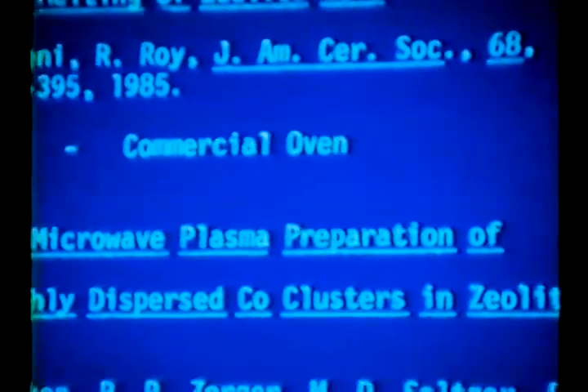Well, here's an example. A picture's worth 1,000 words. Here's this plasma here. Here's the metal carbonyl. So we pull a vacuum through here to get all the gas out. Adsorb the metal carbonyl onto the zeolite. You can see it's a white powder inside of here. Then we have this microwave cavity, and we turn this on. When we're doing the reaction, there's usually a cage around here, because you know microwaves are sometimes hazardous to our health. We have to put a metal screen mesh around this. We put a dewar around this, and we also blow liquid nitrogen onto this material to keep it cool. And then we have these fittings and stopcocks, greaseless lines, so we can bring this into a dry box and load it into a catalytic reactor or into a spectroscopic cell. But it's really quite simple.